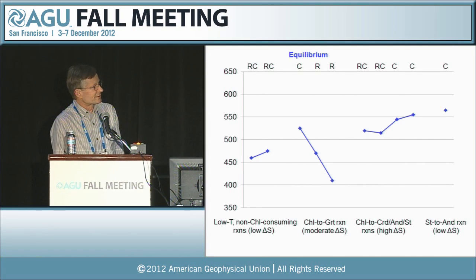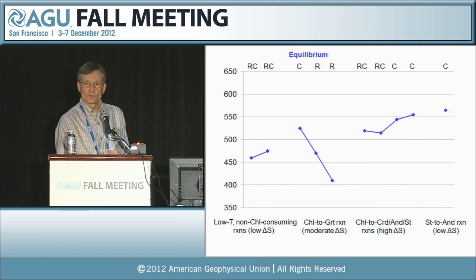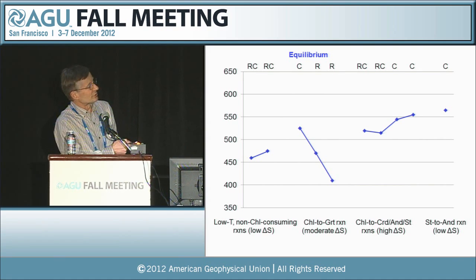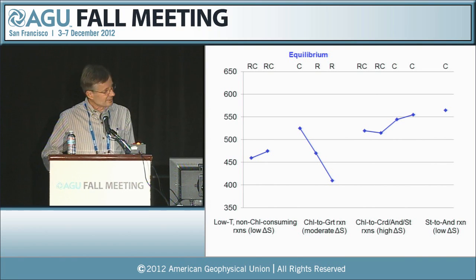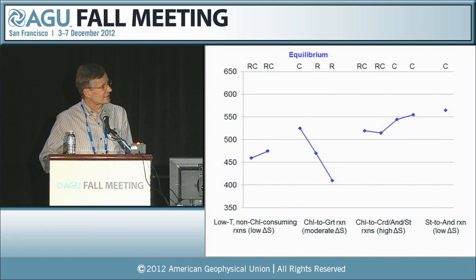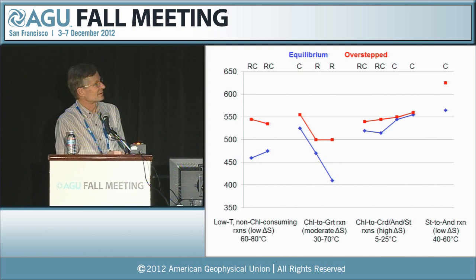So first of all, this is the predicted position of where these reactions would take place, assuming they obeyed perfectly the equilibrium phase diagrams calculated for them. And basically, you can see the temperatures increase from these greenschist facies type reactions up to this one here, which is predicted to occur in the amphibolite facies. So the next thing is to plot where in these studies the reactions actually took place, and that's the red dots here.